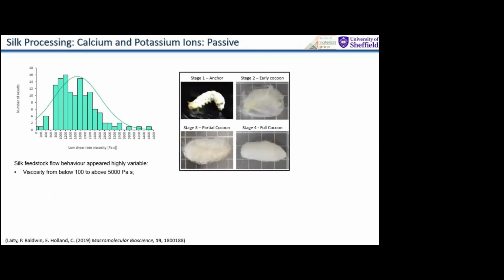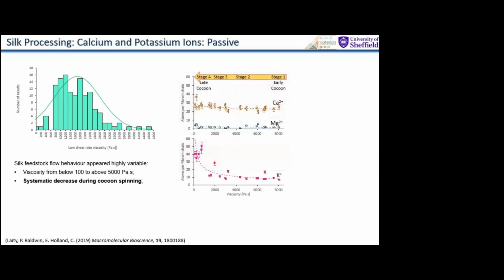And so we started to even get down to the minutiae of when the animal is making this cocoon. And we saw that there was a systematic decrease. As soon as we started recording how far along in the production of the cocoon we tested the samples, we saw this systematic decrease in viscosity.